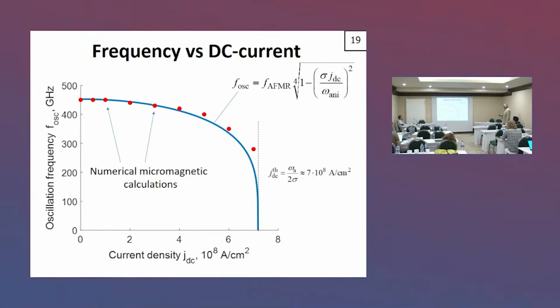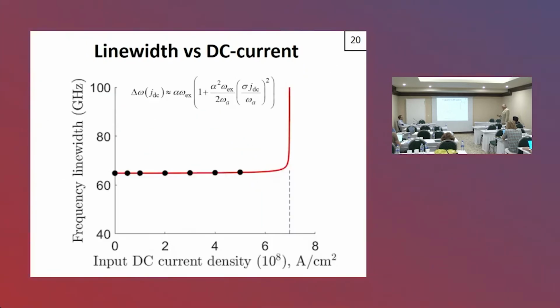We'll also see that the resonance frequency can be tuned by changing the current density. Again, this is not a huge change, but nonetheless, it's continuously tunable. And I saw a new paper submitted to Science where this was fully confirmed experimentally. It will appear probably in a couple of months. The line width is not changing with the current, it is almost constant.